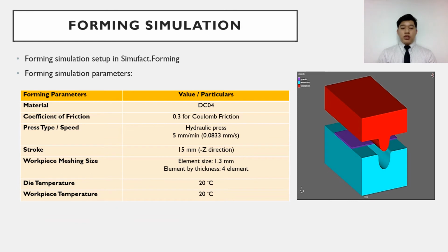As we can see here, the forming simulation setup can be seen in the right picture, which consists of 3 geometrical models: the red geometry is the upper die, the cyan geometry below is the lower die, and in the middle is the workpiece, a 2mm DC04 workpiece. The forming simulation parameters are as below: for the coefficient of friction, 0.3 Coulomb friction is used, and the hydraulic press is set at 5mm per minute speed for a 15mm stroke. For the mesh modeling of the workpiece, 1.3mm element size is used, and the 2mm thickness is divided into 4 elements. The die and workpiece temperature is set at 20 degrees Celsius.